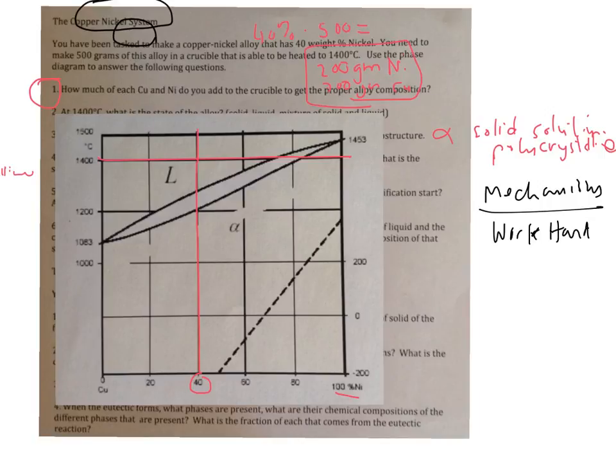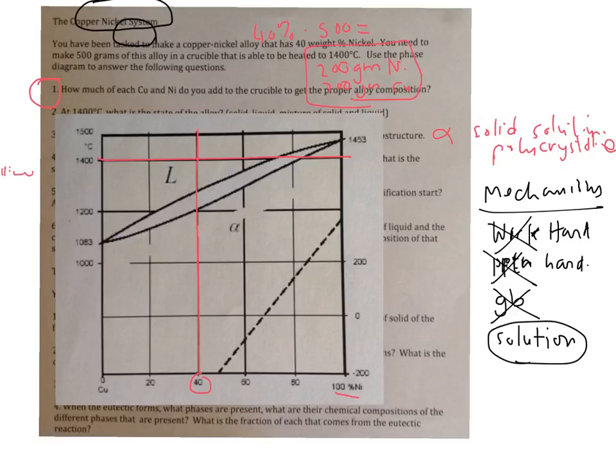So it's not through that. There's precipitation hardening, and precipitation hardening involves actually precipitating a second phase inside this matrix. And since we have a single phase, this alpha phase, it's not precipitation hardening. Is it grain boundary hardening? Well, probably not likely. We talked about that really being active when the grains are only on the order of nanometers. And then you have solution hardening. And this is indeed the kind that you have when you have an alloy that forms a solid solution like copper and nickel.